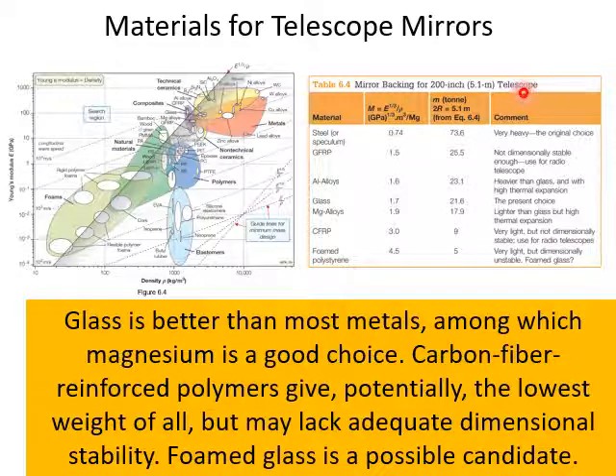So over here you have steel, glass fiber reinforced plastic, aluminum alloys, glass, magnesium alloys, carbon fiber reinforced plastic and foam polystyrenes. So all these materials should be more than enough, complying with the material index. So you need to actually calculate the material index for each material over here. So you can see over here you have steel, which is having the lowest material index value, which is 0.74, and then the foam polystyrene, which is 4.5, which is very good.